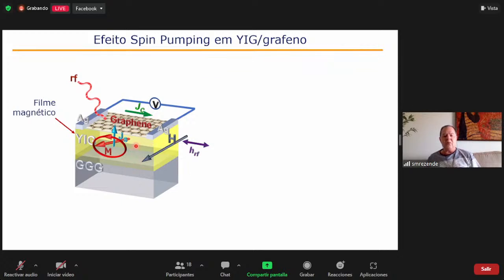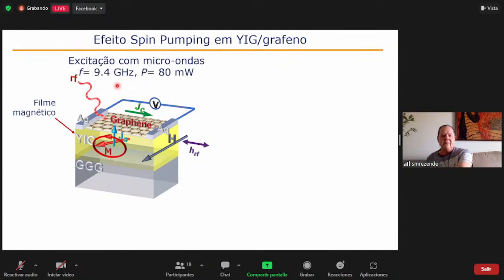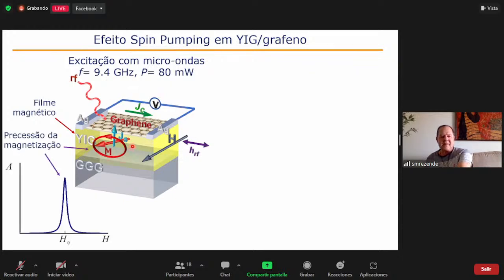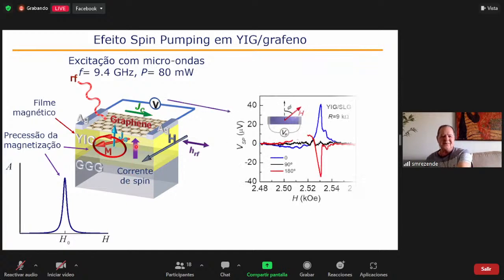The YIG is grown on a GGG substrate, and then by a sophisticated technique we put a graphene layer on top of the YIG film, with two silver contacts, and we do ferromagnetic resonance of YIG at 9.4 gigahertz frequency. The magnetization precesses. This is the result of the magnetization precession. This produces a spin current. I noticed that this slide is in Portuguese. I forgot to translate it.